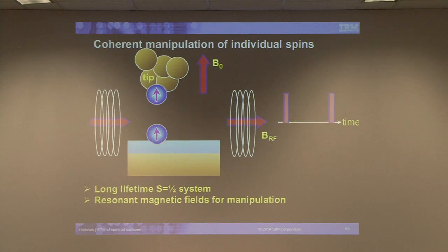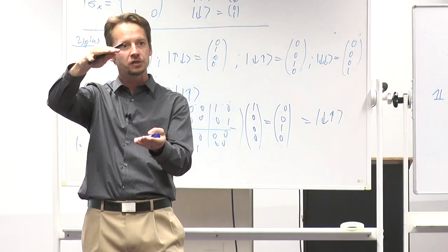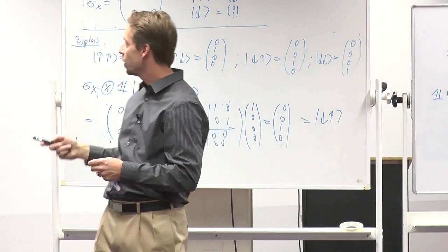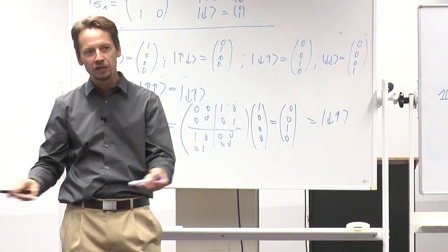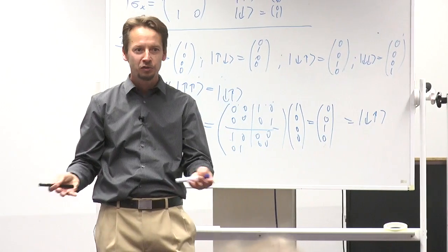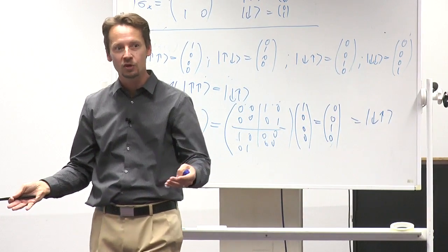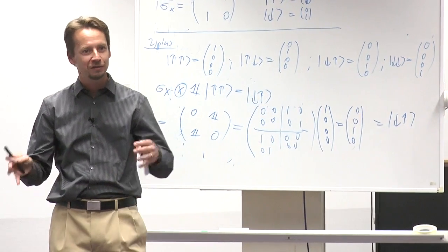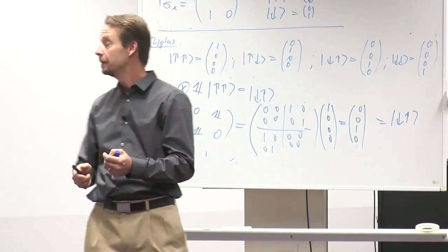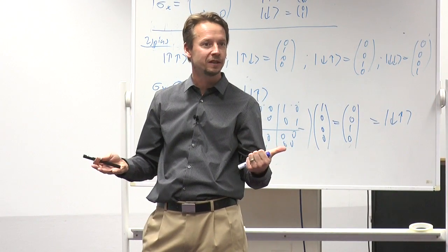And that can give you coherent oscillations between the ground state and that first excited state. Right? So what we need is two things. One, we need to make a system where the relaxation times are long enough that you could have any chance of doing that. If you do this on copper nitride, the T1 relaxation times are on the order of a nanosecond. Way too fast for anything phase coherent to work. Right? So that's one, make them longer, maybe make them a microsecond or something like that.